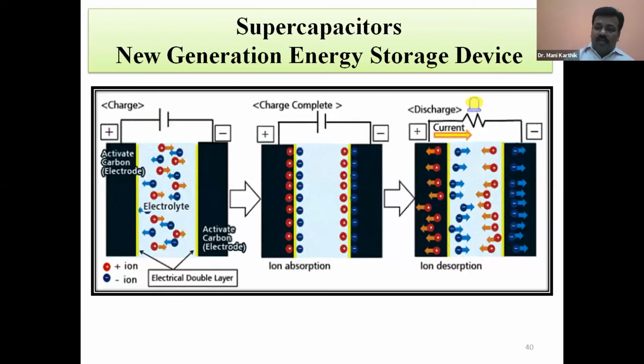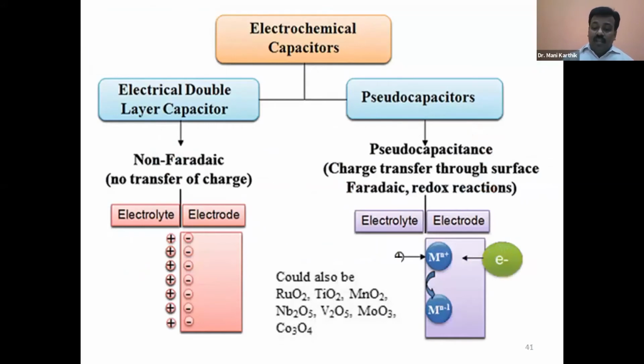But why do we need to go for the higher end? With aqueous, there is something in between, called neutral electrolyte. Neutral electrolyte, such as sodium chloride or sodium sulfate, has no pH variation, whereas KOH is a basic electrolyte and sulfuric acid is an acid-based electrolyte. These are both dissolved in water, so water-based electrolytes are called aqueous-based. As I said, the voltage window is limited. But even though sodium sulfate, Na2SO4, is aqueous-based, you can go for 1.8 volt because there is no pH limitation. So we can go for 1 volt, 1.8 volt, up to 3, then up to 4.5. It depends on the stability window of your electrolyte, even though carbon-carbon is used.